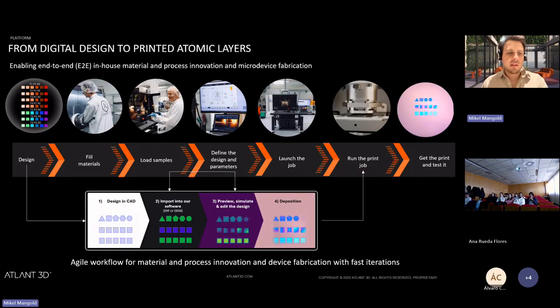This is a little bit the process. So people can design what they want to do. They fill the materials in the machine, in the bubblers. Then they put the samples in the machine. They define the parameters, what they want. We do a simulation on the software. It tells you, well, to get such results, you need to do this and this deposition. Then you launch the job, and basically overnight, you come back the next day, and you have 200 data points of different materials, of different compositions, on one single wafer in one single step.